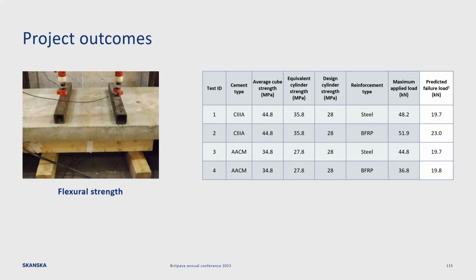Now, it needs to be noted that although we were aiming for a 28 Newton concrete, the actual strength of the concretes were different. So the CIIIA reached 44.8, the AACM reached 34. It's not because we couldn't have the strengths. We were actually aiming for a low-strength concrete in this trial because on site we wanted to see the performance, and we wanted it to crack. We wanted to see how much load it could take. Would one perform better than the other? We could have put a very high-strength concrete in and not seen any detrimental effect for the next 25 years, but that wouldn't have been very helpful.